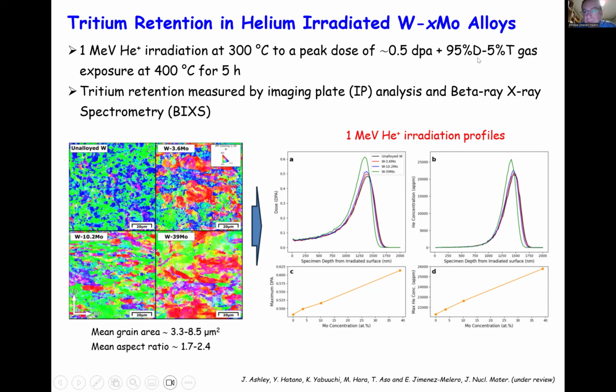Now, since the tritium is radioactive, we can measure it with image plates and with what's called BIXS, as I will show you in a minute. These are the materials or microstructures that we made. Those materials are made by powder metallurgy, and then afterwards you hot roll the material at high temperatures. We can simulate the damage profile and the helium concentration